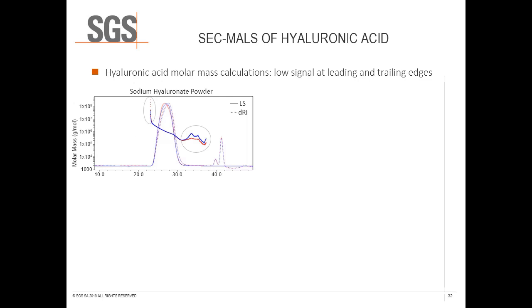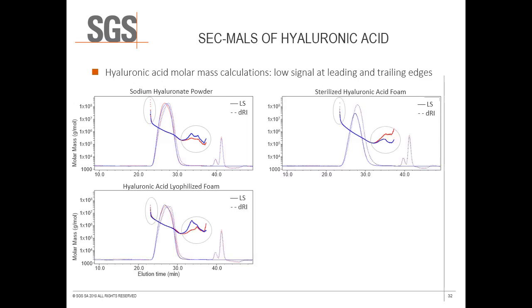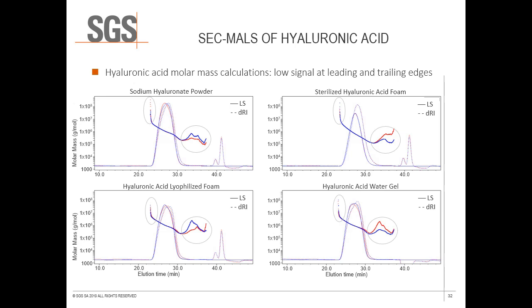Shown here are the molar mass plots for duplicate injections of the submitted hyaluronic acid samples. Seen in the tail of the peak is the characteristically erratic results in the integrated region for which there is little instrument response from one detector or the other. In this case, however, the increase in calculated molar masses in the peak tail may not be attributed to low signal and detector noise alone, but may also be indicative of anchoring. The slight irreproducibility in the peak apex of duplicate injections shown for 3 of the samples is a good example of viscous fingering as discussed before.